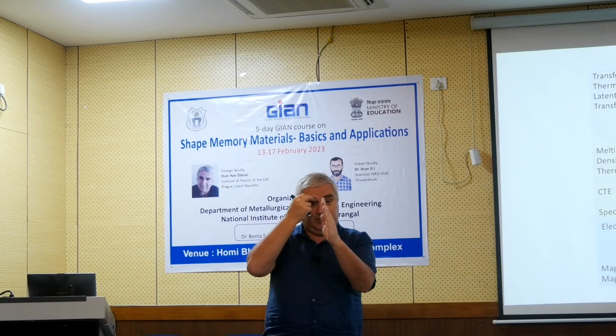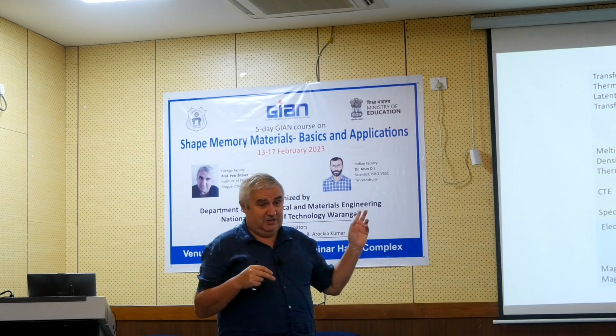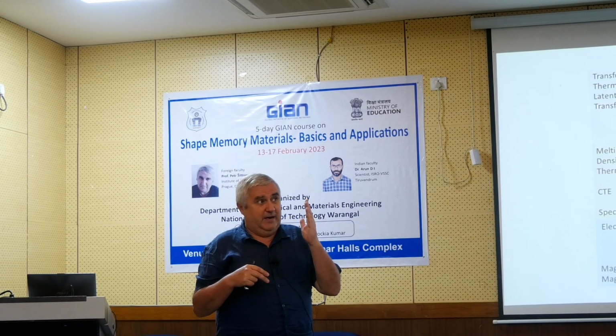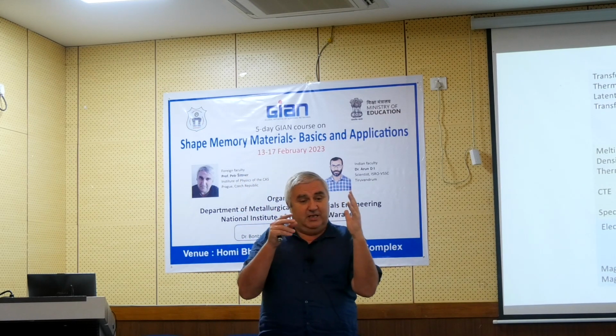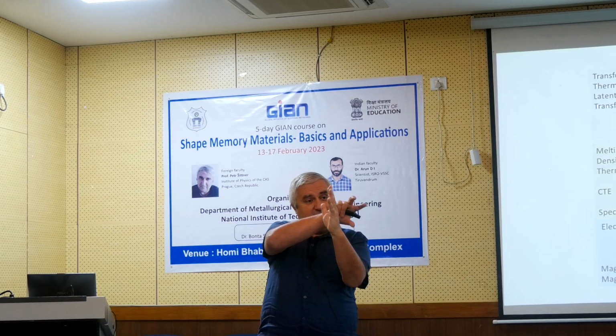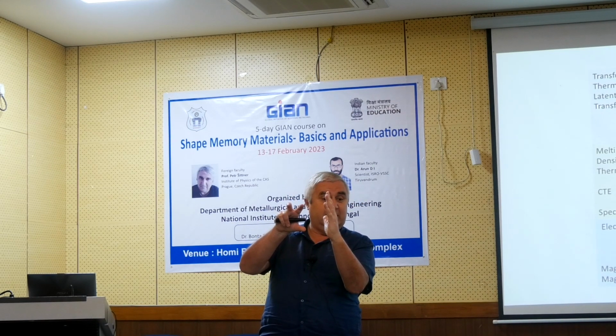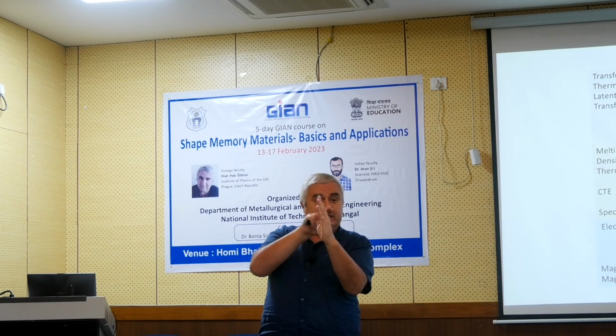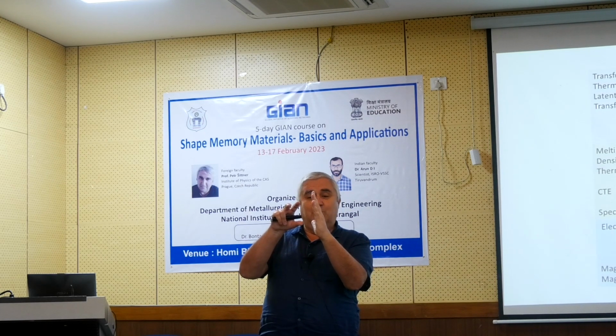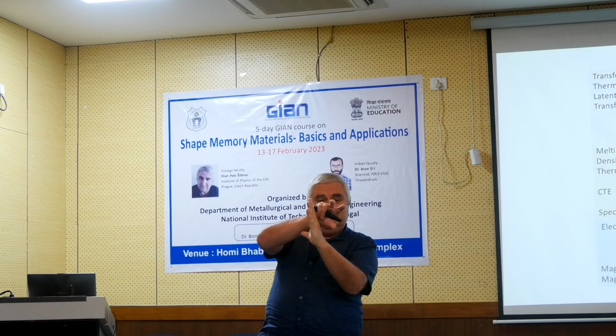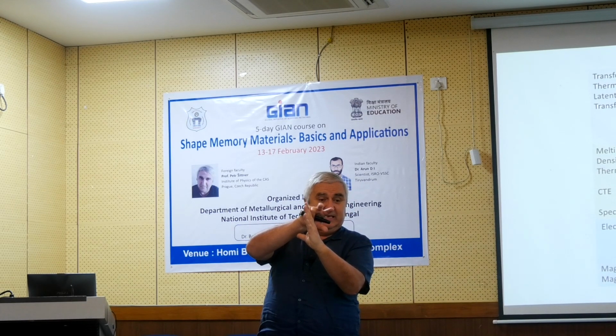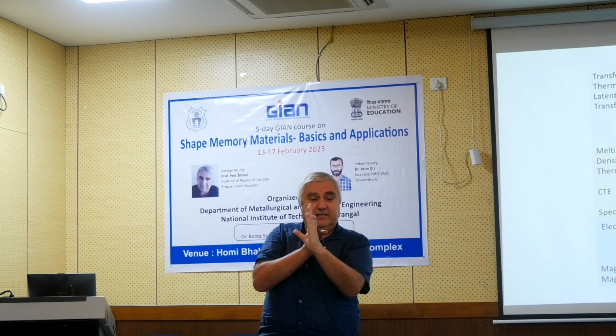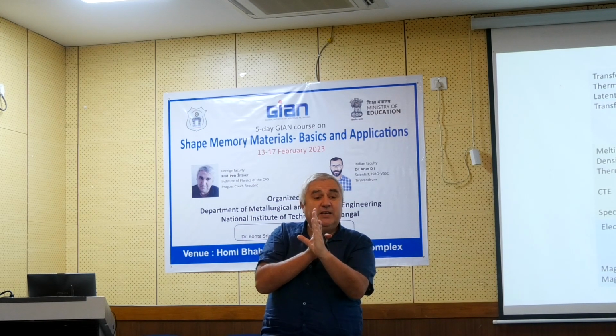I spoke about it yesterday, and I will be speaking again because it's very important in the end of this talk. Now this depends on the strains, which depend on the lattice parameters of the martensite. And by adding the copper to nickel titanium, you change the lattice parameters of austenite as well as martensite, and it can basically do almost single crystal martensite here and single crystal martensite there in nickel titanium copper. And then this interface easily makes the habit plane, even under stress.